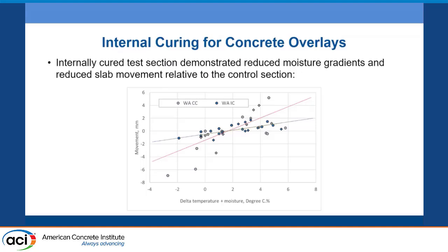And the gradients that they measured through instrumenting the slab appeared to be less in the internal curing test sections. And with the LiDAR measurements, they also noticed that did in fact correspond to less overall shape change in the slab. So it appeared to not have as much of a built-in curling or warping profile, and then it didn't experience as much movement between measurements when they went out at different times of year and different times of day relative to that of the control section.